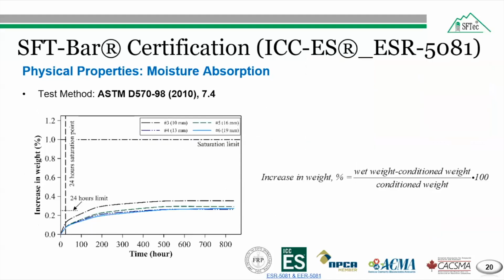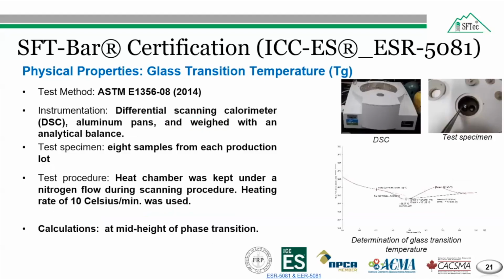For the helical wrap glass fiber reinforced polymer bars, the average measured water absorption at 24 hours and at saturation was lower than the requirement values in ASTM D7957, as we can see from this figure. For the 24-hour limit, it is around 0.25%, and we get a much lower value. At saturation, the limit is 1%, and the value is below 0.4%. The SFT-Bar specimens were tested in accordance with ASTM E1356 to find the glass transition temperature.